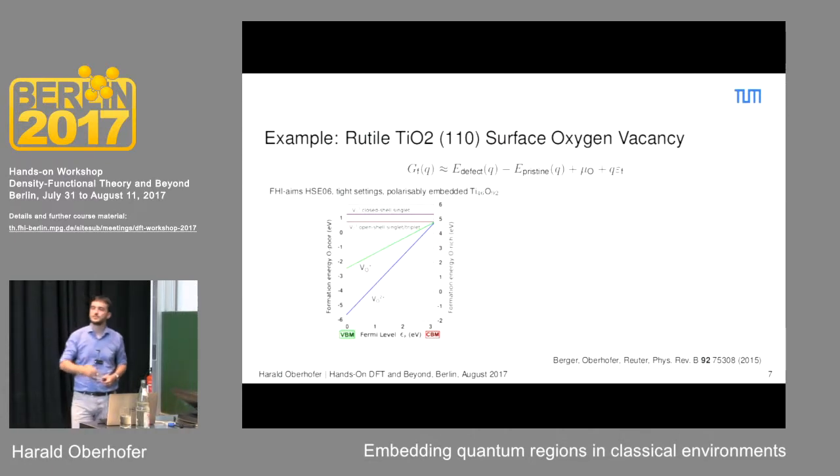If I take away the oxygen, which in the extended system is negatively charged, it grabs a couple of electrons from the titanium. You can either leave these electrons behind, leaving a neutral defect, you can take these electrons out, or you can take one of them out. That gives rise to 3 differently charged defects, and there is a 4th one here, which is just us looking at whether the neutral one is a singlet or a triplet state. So we have a doubly charged defect, a neutral defect, and a singly charged defect.